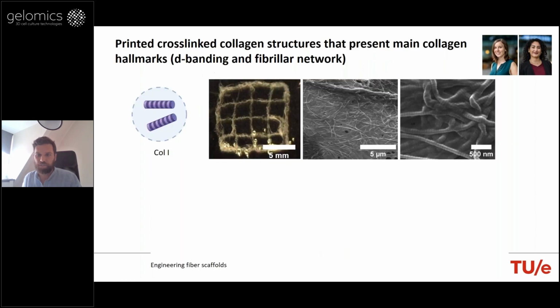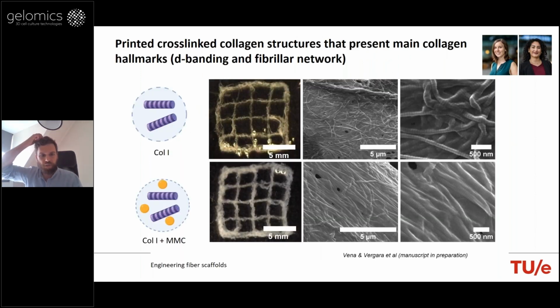It was very interesting for us to see that when we compared structures printed with or without the macromolecular powder, we observed that in the presence of the macromolecular powder, we achieved basically denser and more aligned constructs. So you can see here by these scanning microscopy images of one single filament or one section of the printed construct. So typically, this was the contribution of the macromolecular crowding.